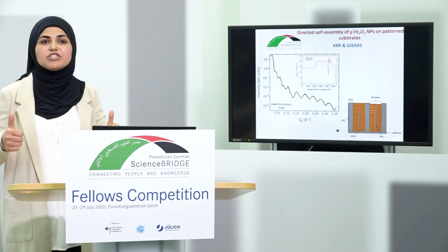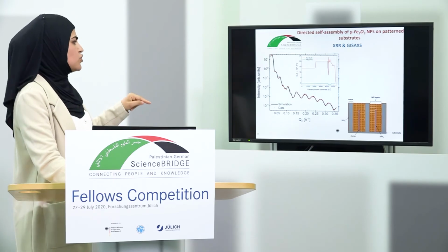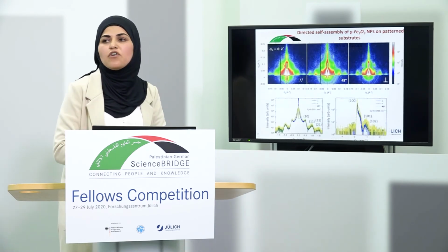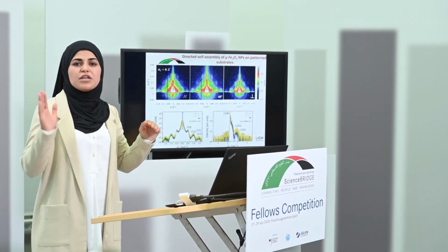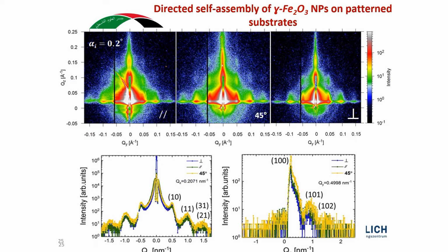Second example: depositing these superball nanoparticles. First of all, I checked if I have layering inside the groove by measuring reflectometry. From the fitting of the data, I found that I have homogeneous layers inside the groove with the same thickness, and there is some magnetic interaction between these layers. To get information about the lateral correlation, I measured GISAXS in 3 different directions to see if we have a 3D single crystalline arrangement of nanoparticles.